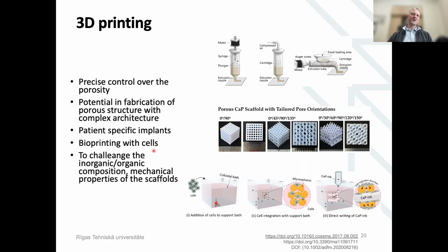But there is still a challenge of the inorganic phase composition and the mechanical properties of the scaffolds. So now we have two parts in the development. From one side, we are very close with the material chemical composition and also the mechanical properties to the bone, but we are lacking this degree of freedom to produce a nice porous structure and desired shape. From the other side, we have this degree of freedom from 3D printing to get the shape and the porosity, but in this case the mechanical properties and also the composition, meaning the inorganic and organic phase ratio, is really far away from what it is for the bone.